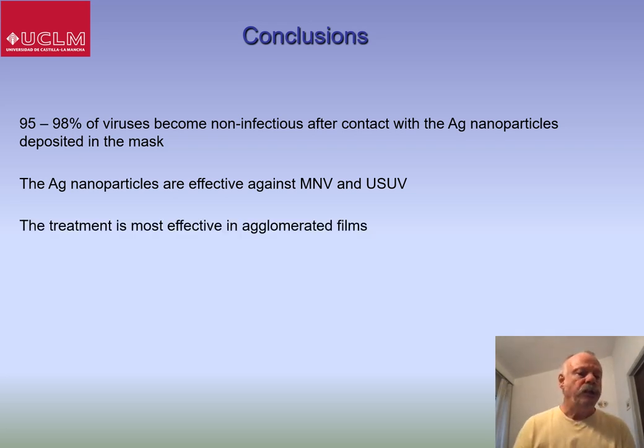The treatment is most effective in agglomerated films. Now, this was a surprise. In the early parts of the project, we were very keen to try and keep low deposition so the silver nanoparticles were completely separate. But it seems the best performance is with the densest films. And what this shows, or seems to show, is that the virus, remember, this is the rescued virus that has come away from the cloth, the interaction with proteins is sufficiently strong for the virus particles to pull the silver nanoparticles off the agglomerated film.